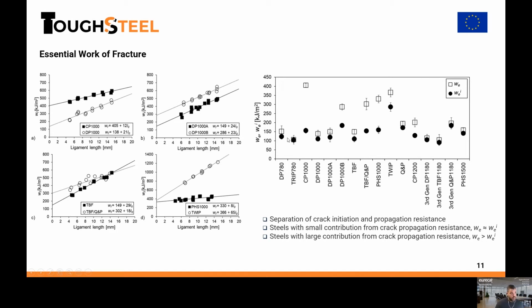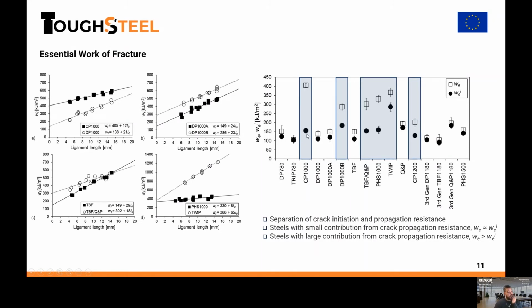This is a summary of results for a wide range of advanced high strength steels. We can see that while some materials present a small contribution from crack propagation resistance after the initiation, the fracture toughness at crack initiation, represented by these black circles, and the specific essential work of fracture, the empty squares, are pretty much the same, so almost equivalent. However, there are other materials where there is a large contribution from crack propagation resistance after initiation. In this case, highlighted here in blue, we can see that there's a large difference between the specific essential work of fracture and the initiation toughness. Then in these materials, the essential work of fracture defines much better the overall fracture performance, and a single initiation toughness is not sufficient to define the fracture performance of this kind of materials.